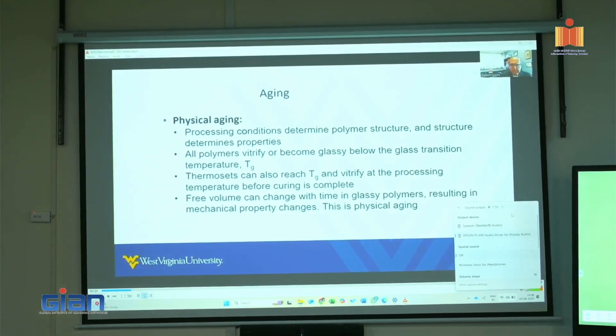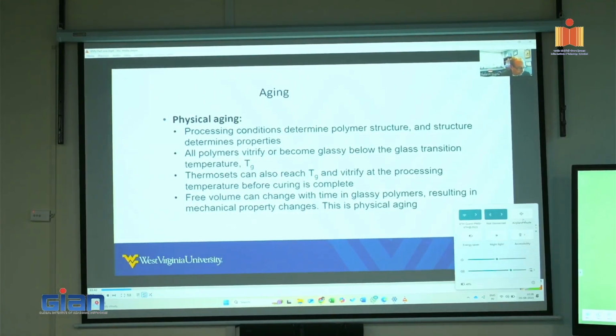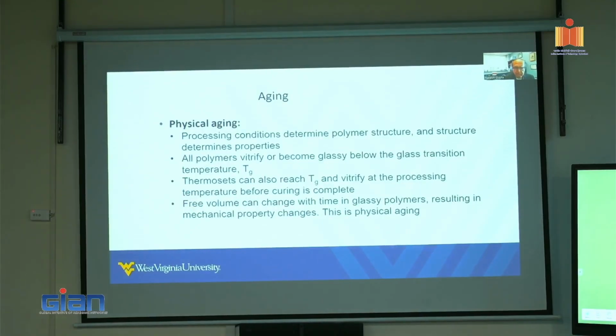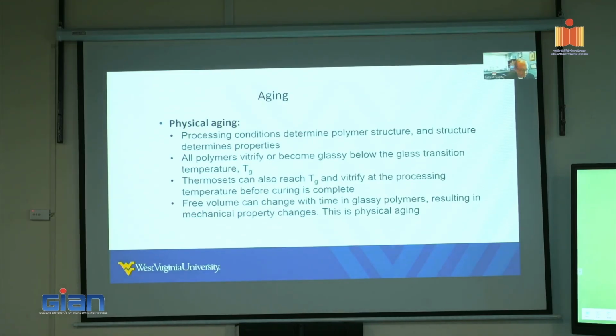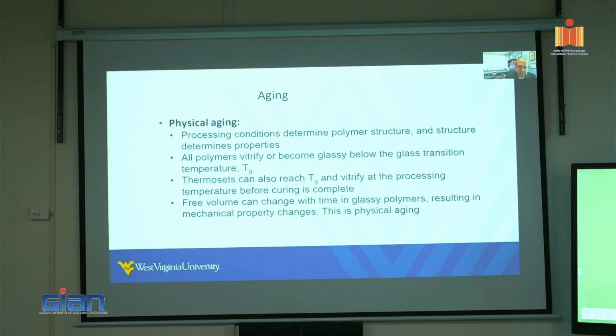Early on, the properties can change because of what we call physical aging. The paradigm in the polymer community is that processing conditions determine the structure and structure determines the properties. Since processing is done over a short time scale, the structure that results typically is not an equilibrium structure. And as time goes on, the structure tends towards the equilibrium. Depending on the temperature and time of processing, the material may not be fully cured.